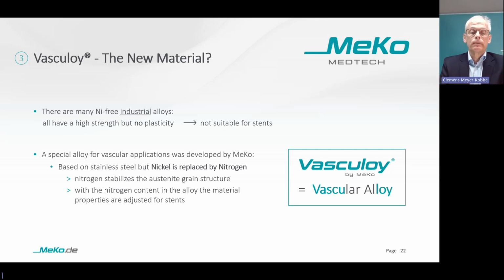We call it break elongation. For example, coronary stents are crimped down to less than 1 millimeter and expanded in the human body to more than 3 millimeter. During this high deformation, the stent struts should not break. Therefore, we need the plasticity. All implant materials like stainless steel, which is 316L, and the cobalt chrome alloys L605 and MP35N, or the platinum chromium alloy or nickel titanium, have a significant portion of nickel in the alloy. So all stents which are currently on the market have a significant portion of nickel.